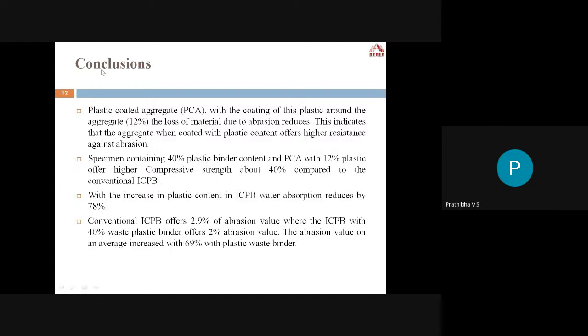So the conclusion is basically, as I said, the main objective of incorporating plastic coated aggregate instead of raw aggregate is to make the aggregate more resistant to impact and crushing, and also abrasion. The abrasion value is reduced by 69%. And next, coming to the compressive strength, with the increase in plastic content, the ICPB block with 40% plastic binder will have a 40% increase in compressive strength.